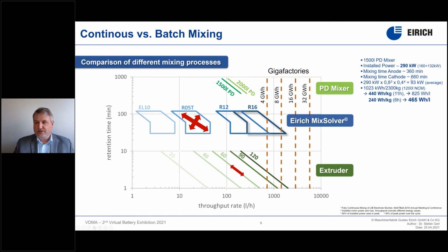Retention times of 6 to 11 hours. And if we calculate an average energy consumption of 93 kilowatt over the time, then we end up with 1,023 kilowatt hour for one batch of 2,300 kilo, for example, if we have a cathode material. And by this, we can calculate, even in a very positive way, with 6 hours, an energy consumption of 465 watt hour per liter. The extrusion systems, with their very short retention times, promote that they can run with about 25 watt hour per liter.